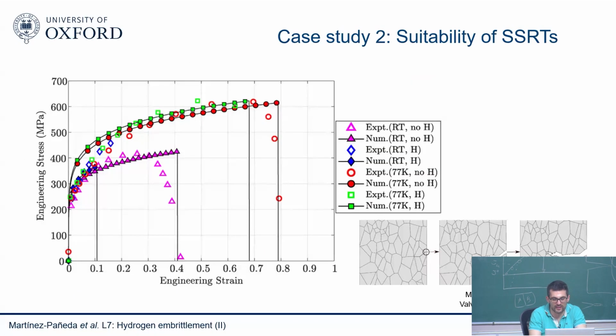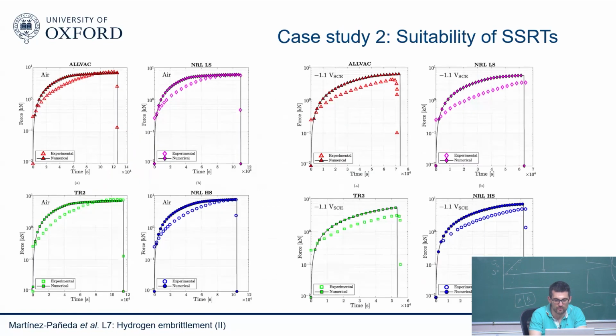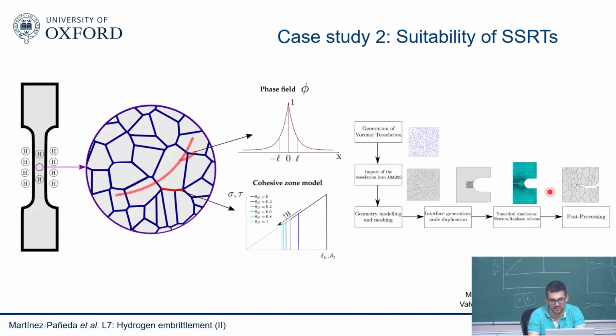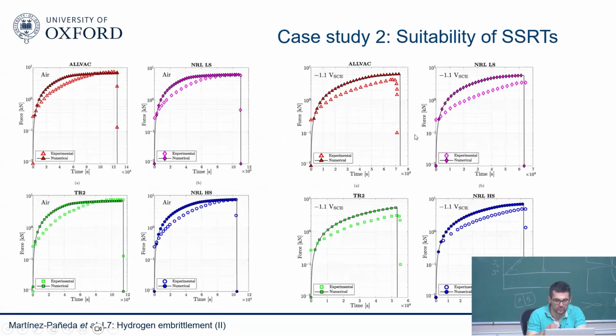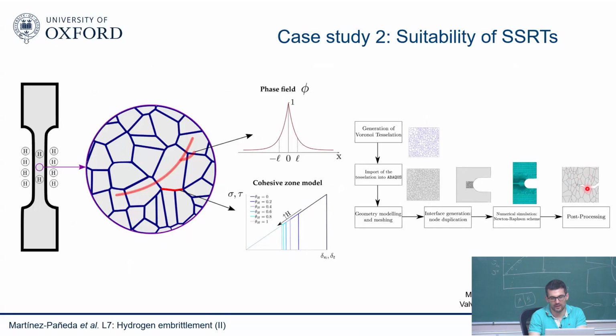And so this again confirmed basically our expectations. It told us that we could see the cracking occurring like this. You can see this is an element of the simulation, so you see crack growth along the grain boundaries. So again, with this more microstructurally resolved model, we were able to capture how those cracks originated in grain boundaries when you brought the hydrogen in. We could see how those cracks propagated as the test continues, so that you get initiation. We confirm basically what we saw with the more crude macroscopic model.